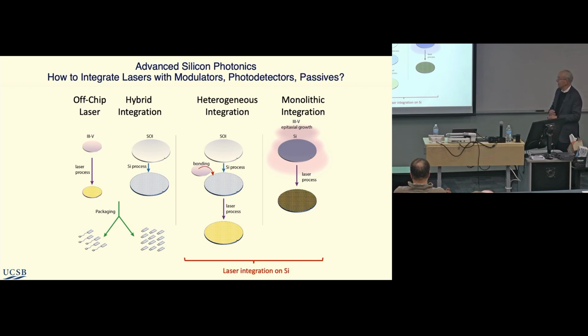The other approach is what I call hybrid integration, with lasers and PICs close together. I'll show a lot of examples, but it's only one step. Here, we're bonding III-V materials onto SOI silicon photonic wafers and etching off the substrate. The alignment is very coarse—you just have to have the gain material where you need it, then use mask alignment after that to fabricate the lasers and the rest of the silicon photonics. This has been commercialized by a bunch of companies: Intel, HPE, Juniper, and others.